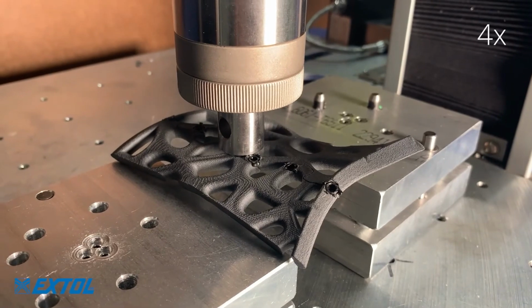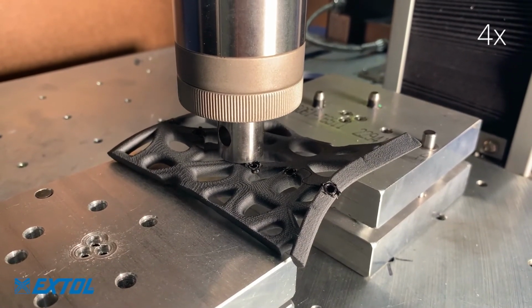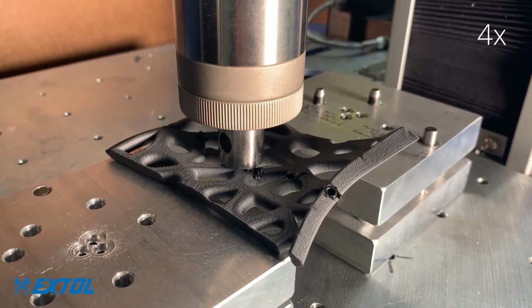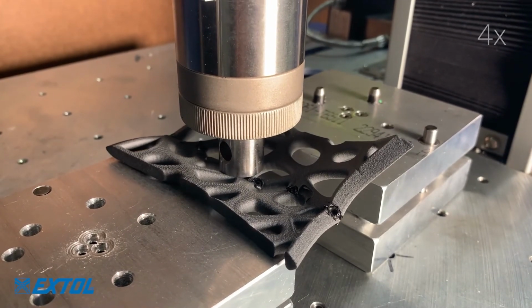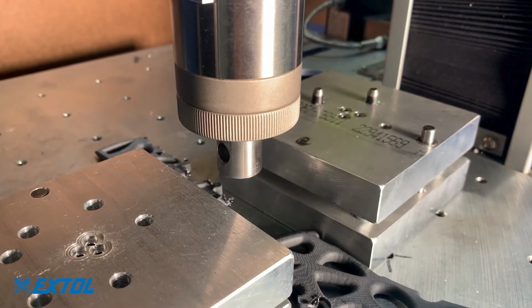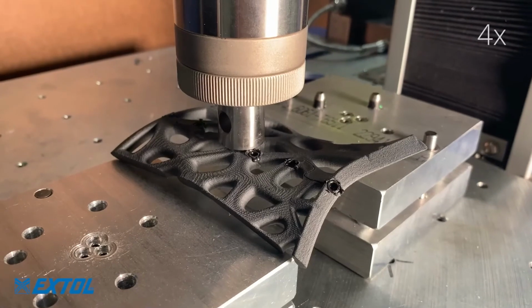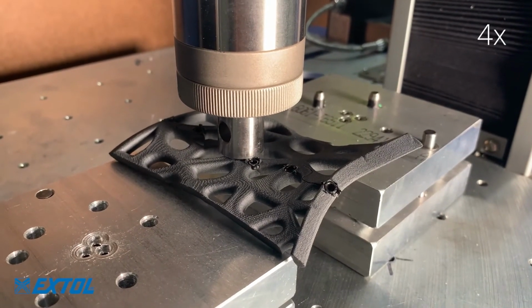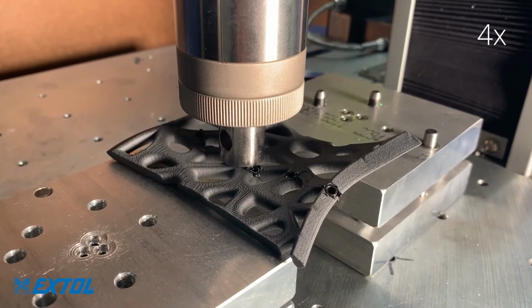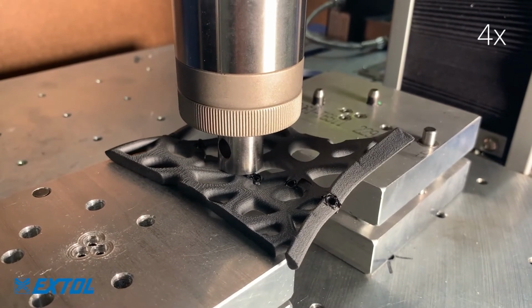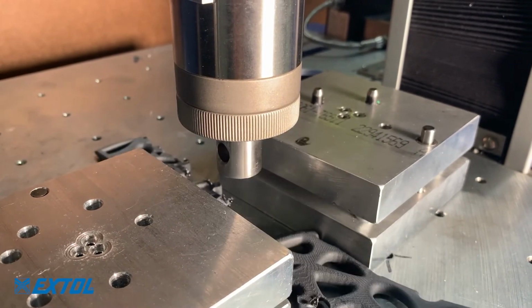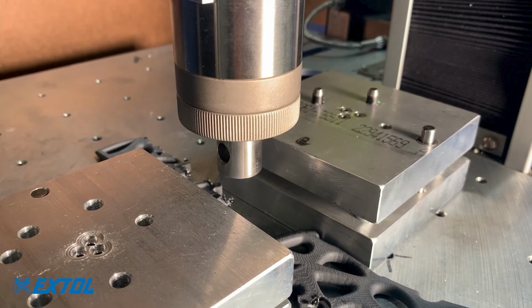But adhesive tends to be really brittle in joints like this. The great thing about polypropylene is the joint is being joined by the polypropylene itself. So we still get that ductility in the joint that we're used to having in a polypropylene part, and we don't mess that up with a really brittle adhesive. And part of what breaks in this is actually the parent material of some of those jigsaws as well.